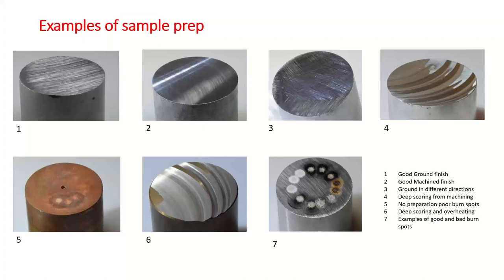And then the final one, number seven, is quite a good example of burn spots, with examples of good ones and bad ones. The black ones, the three at the back there, are examples of a very good burn spot. People will tell you the black is carbon, but it's not carbon, it's actual condensate. As the plasma is created and then cools down, the material it's taken up from the surface drops back down, and in most cases that will drop down as a black sooty residue, but it's actually the material that you've measured and not just carbon.